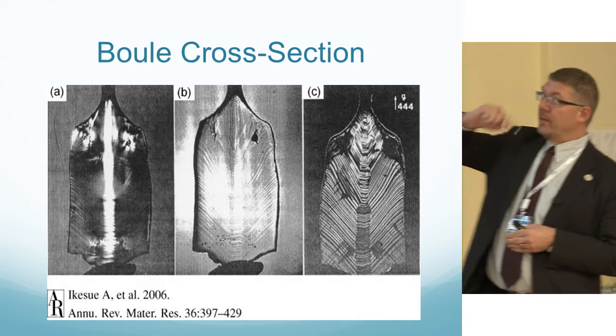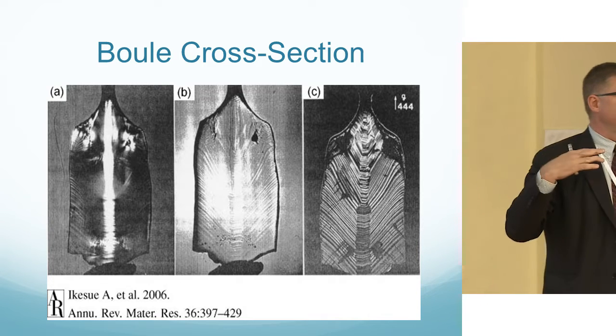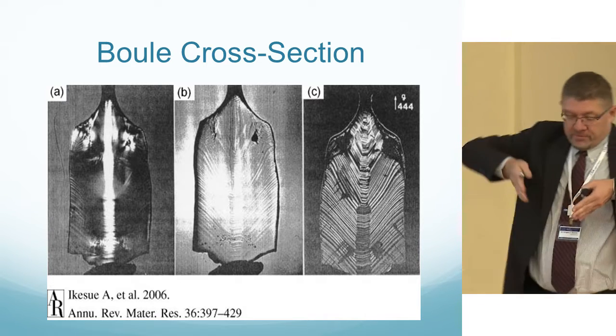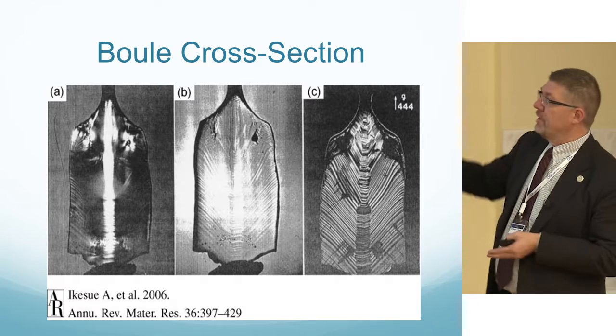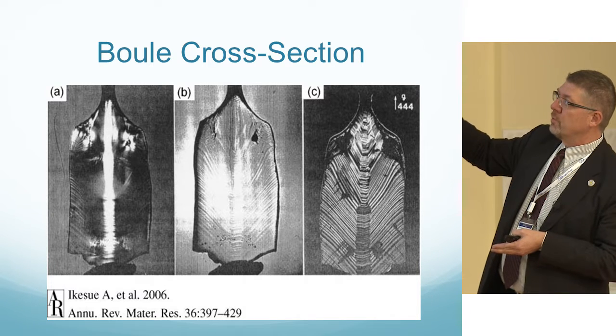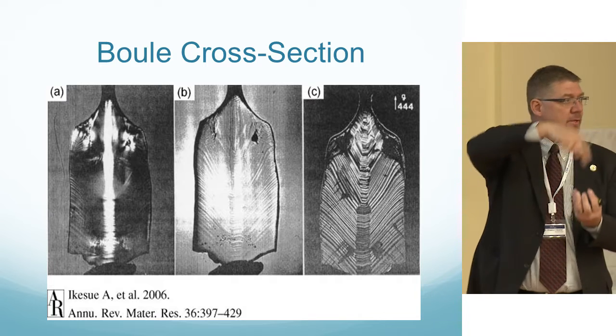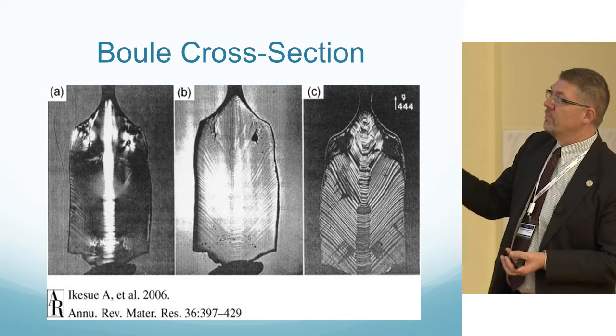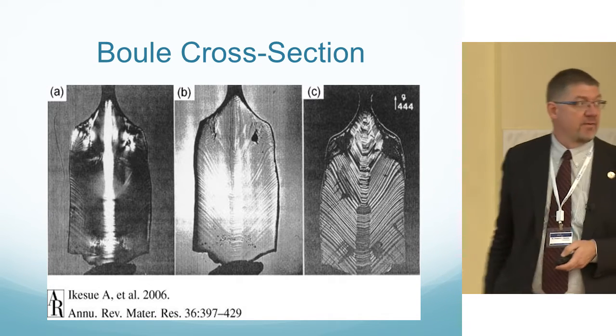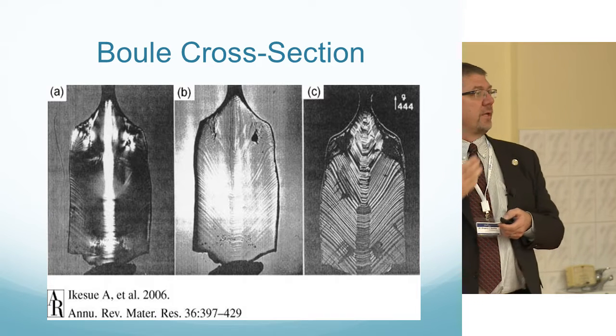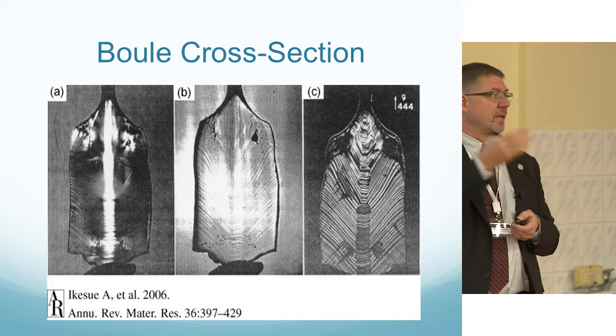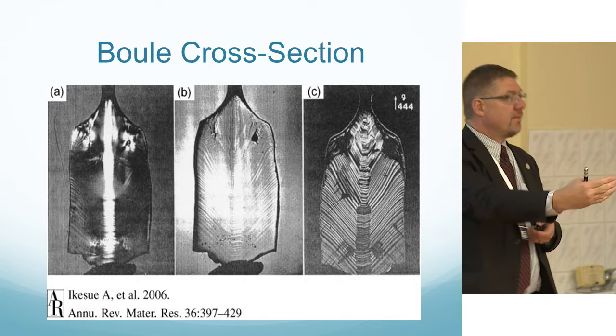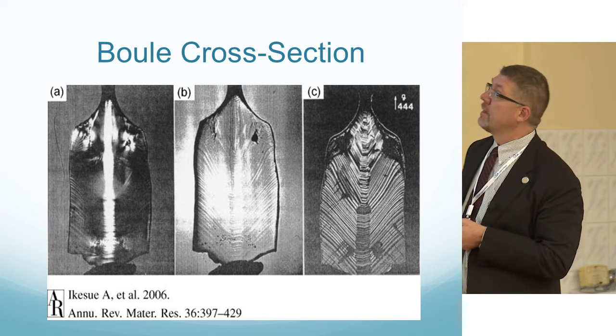This is what the boules look like if you cut them lengthwise and look at a Schlieren interferogram. Because these grow down into the melt with an interface, that interface is mimicked as you pull the crystal up and rotate it, just like growing sugar candy as a kid. So these areas can cause there to be defects in the laser, which then give rise to either radial or tangential distortion components of the wavefront propagating down the rod.